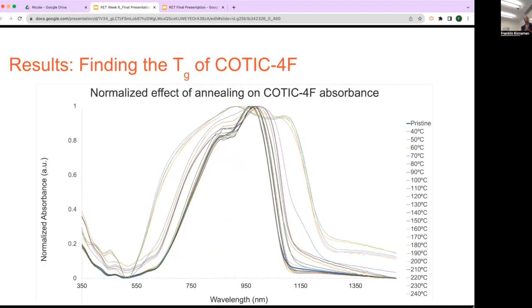Then when we normalize this data, which gives us the meaningful data, we can see these trends again. We can see that above 150 degrees, we get this huge curve, much broader. And then at 120 and 130, we also start to lose that first shoulder that seems significant. Because these are deviating so much from the signature absorption of this material, we actually ended up excluding a lot of these temperatures above 120 degrees for doing that final Tg calculation.